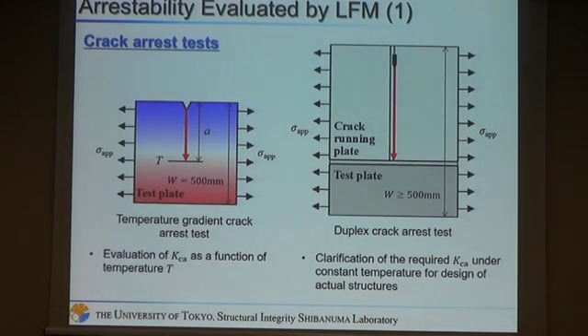The arrestability of the steel plate is evaluated by a crack arrest test based on the linear fracture mechanics theory. There are two types of the arrest test, temperature gradient type and duplex type. The temperature gradient crack arrest test is used for the evaluation of arrest toughness KCA as a function of the temperature. On the other hand, the duplex crack arrest test is used for the clarification of the required KCA under the constant temperature for design of actual structures.